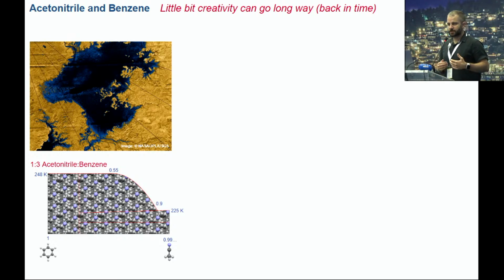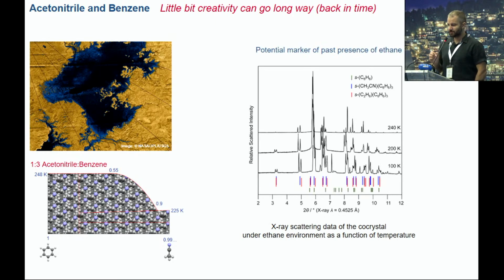So we did an experiment in which we mimicked raining down ethane on top of our co-crystal, and then we did another experiment in which we soaked the co-crystal, and then we did another experiment in which we created this co-crystal in liquid ethane just to see how it would react, and then dried the lake. We see that we have splitting of the diffraction peaks, as expected if we introduce ethane. We haven't solved this crystal structure.